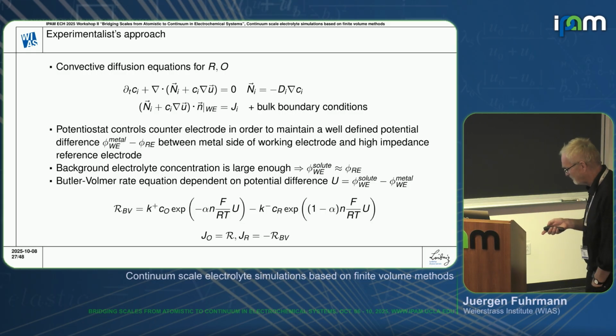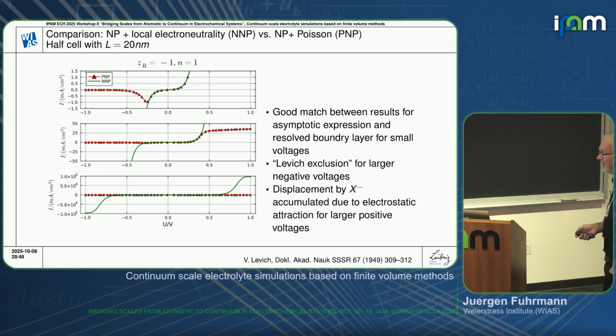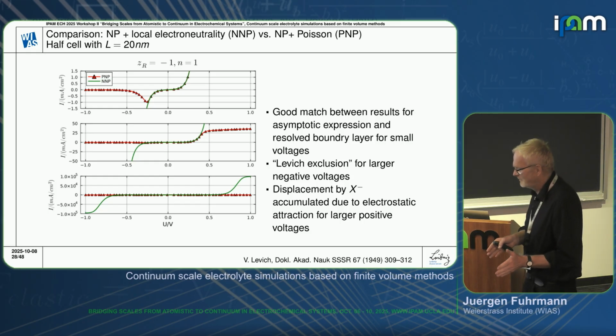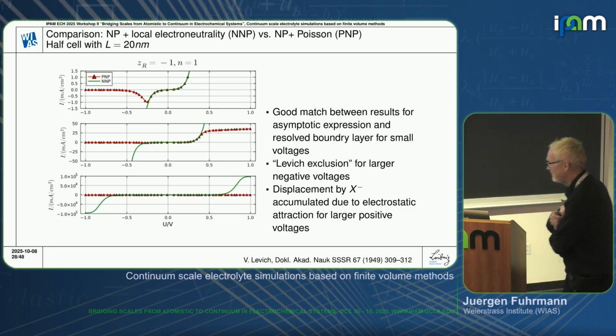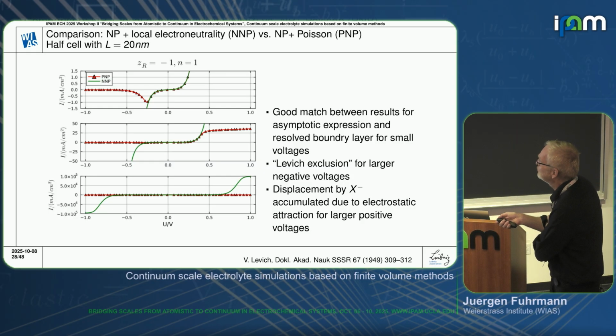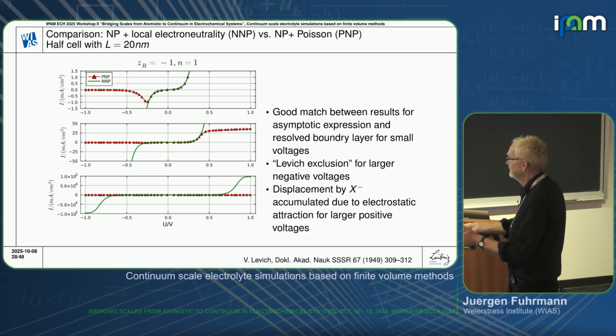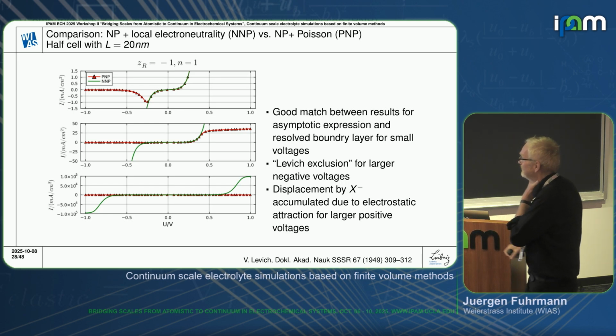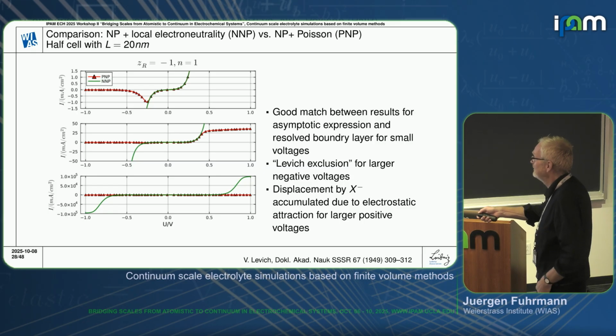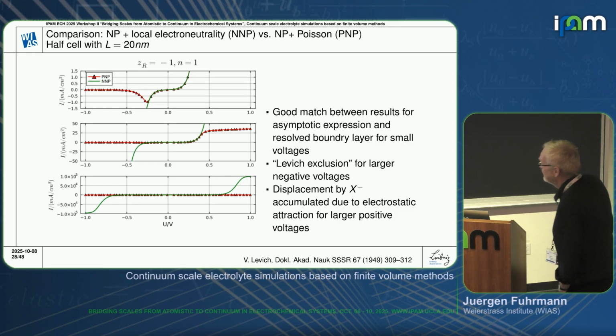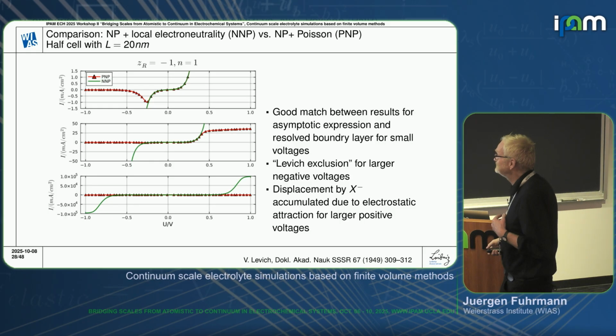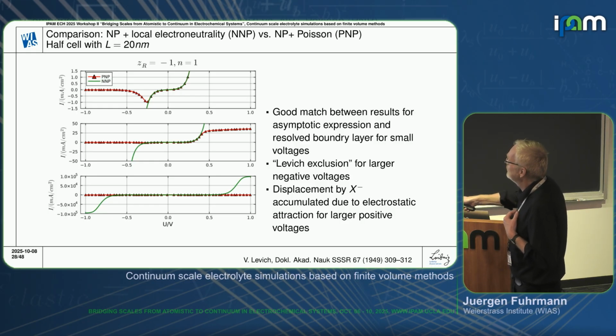This is the way we can make the link to electrochemical experimentation. So I tried out how this asymptotic transition from the double layer scale to the electroneutral scale plays out. These are applied potentials. This is static voltammetry, so it's just stationary solutions calculated for every one of these potential values. The green curve is our electroneutral model with the Butler-Volmer equation, and the red curve denotes the model with the fully resolved boundary layer. And we see that at least for a reasonably small potential range, they match exactly.